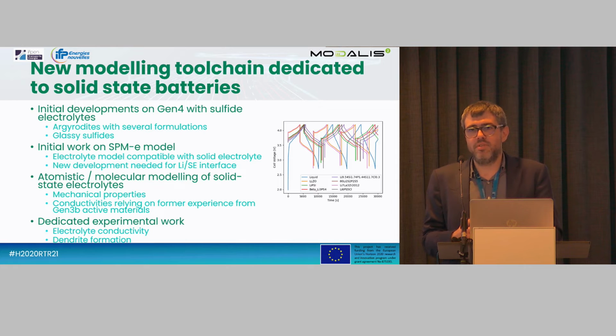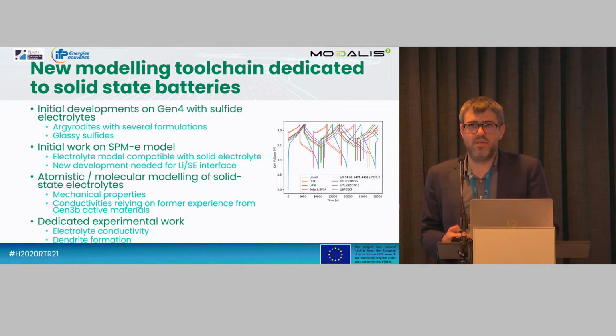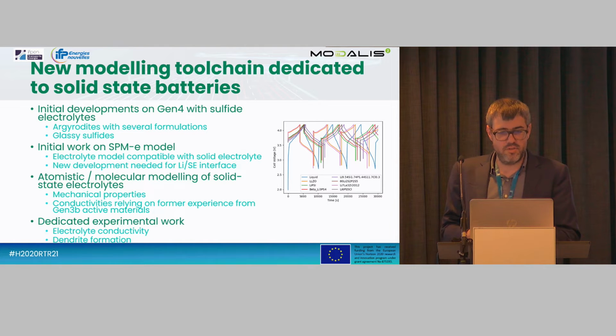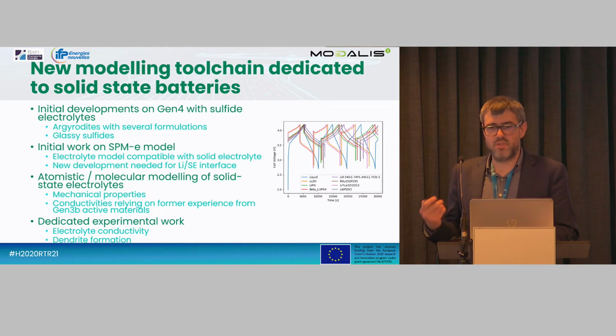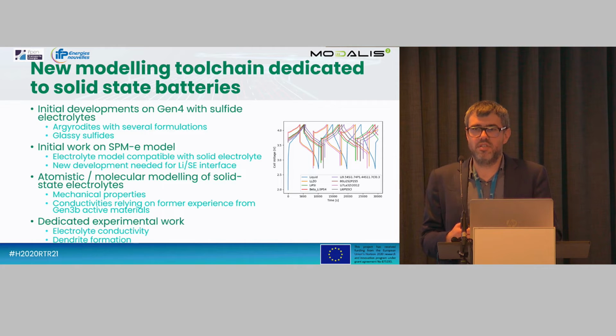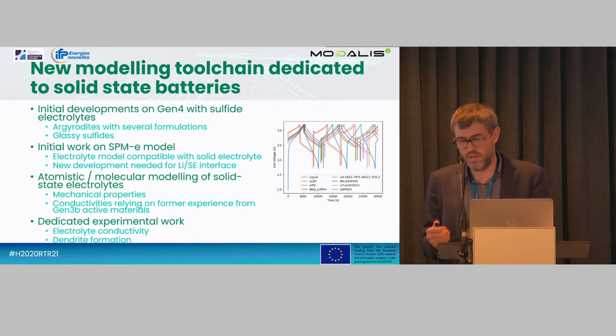So the good point is that the electrolyte model that we are using is in line with what we expect for solid electrolytes. So the development is lighter. However, we need to develop a completely new interface for the negative electrode, especially as we have no particles, so single particle is not really well suited for this kind of approach. And we need to create a new framework for this kind of approach in order to account for the specific surface behavior of the lithium, and how it changes over time due to dendrite formation or mostly surface formation. The atomistic and molecular modeling will focus on mechanical properties and conductivity predictions for the electrolytes. And we also have to develop the experimental work in order to make sure that the experiments that we are doing will be comparable in the end with what we expected from the calculations.